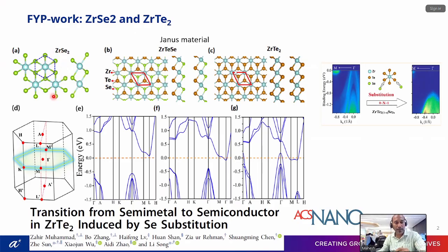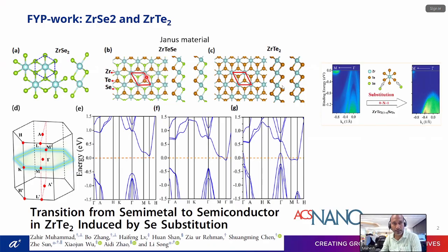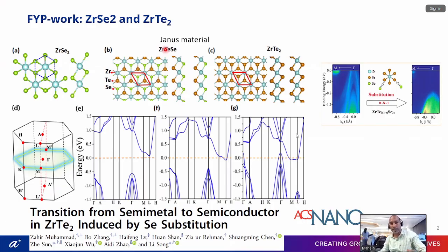zirconium selenide has a hexagonal structure and is a semiconductor with a band gap that is not wide, like 0.7 eV, 0.5, where you can tune the band gap with tellurium. You can tune a few percent of tellurium, and at 50 percent it is a Janus material. A Janus material is one where one layer is Te and another layer is selenium. So it's a perfect semi-metal, even at 50% tellurium. More tellurium makes the band gap much lower and a more metallic kind of transition, with an inverse band.